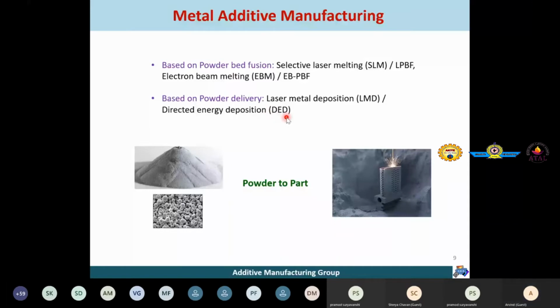where in the powder bed fusion process, we first lay down a layer of powder on the build plate and selectively apply laser to melt and consolidate it to create the final part of that layer. In powder delivery based process, we actually feed the powder particles coaxially or through multiple nozzles simultaneously along with the laser. We do not lay down any powder layer there. So the fed powder particles meet at the merging point of the laser at the substrate, and there they melt and form a melt pool, and then resolidify to create a deposited solidified layer. And this is followed in a layer-wise manner.